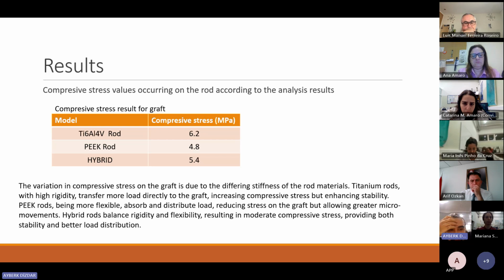Titanium rods with high rigidity transfer more load directly to the graft, increasing compressive stress, but improving stability. PEEK rods, being more flexible, absorb and distribute the load, reducing stress on the graft, but allowing more micromotion. Hybrid rods balance rigidity and flexibility, resulting in moderate compressive stress, providing both stability and better load distribution.